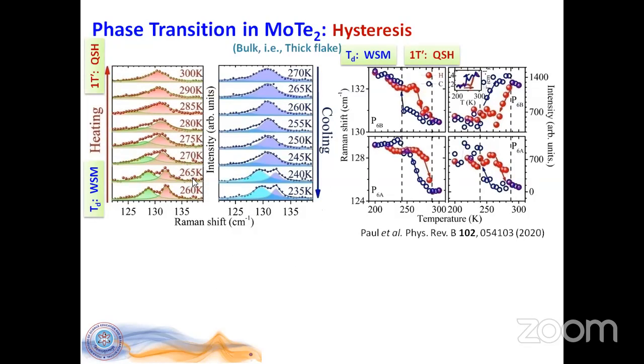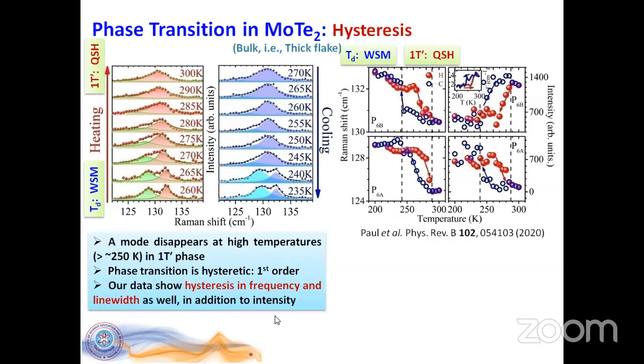So we plotted here not only the intensity of the two modes as a function of temperature, which is given over here. So this is the 6A, that means the left one, and the right one is the 6B. So 6A and 6B, the intensity, as you can see, shows a hysteretic behavior with temperature. And not only that, even the Raman frequency of this vibration also shows a clear hysteresis in temperature. So these are the signatures, and we know that this phase transition is first order in nature.